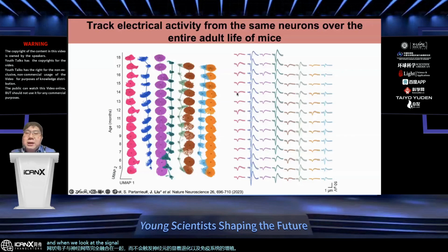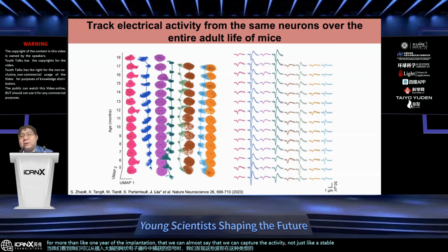And when we look at the signal that we can capture from those mesh electronics implanted into the brain, we found that the waveform is remarkably similar over more than 1 year of implantation, so that we can almost say that we can capture the activity not just stably from the neurons, but almost stably from the same neurons.